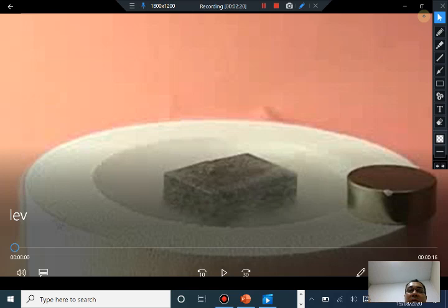The boiling point of liquid nitrogen is about 77 Kelvin. So just by cooling it with liquid nitrogen, you can make this material superconducting, because its transition temperature is 90 Kelvin, and liquid nitrogen is more easily available compared to liquid helium. So it makes doing this experiment reasonably easy.